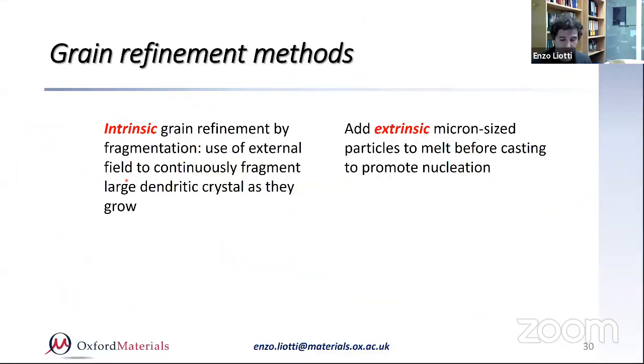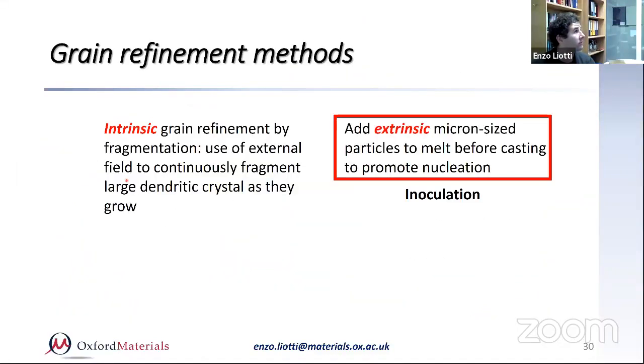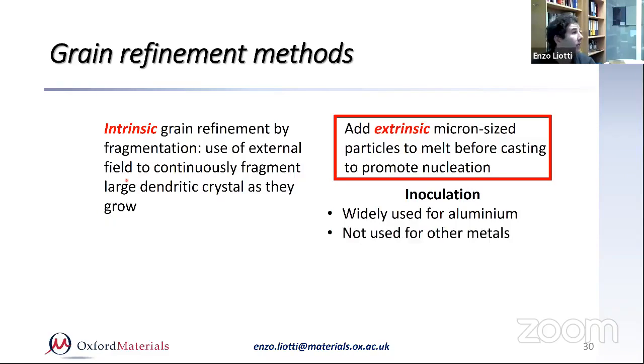The second case study I'm showing is the one of extrinsic grain refinement, regarding inoculation. The use of TiB2, especially in the aluminum industry, is widely applied, but it's not very widespread for other metals. There are not many grain refiners for steel or for cast iron, for example, right? And also the efficiency of the inoculation is very low.